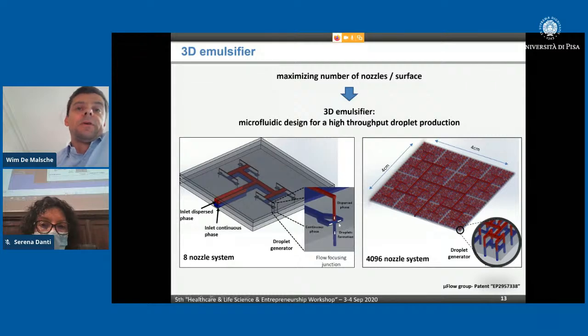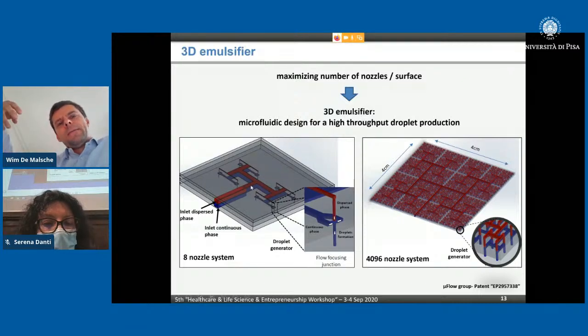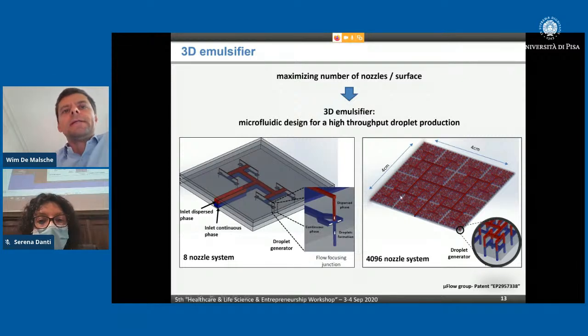The solution to this is what we've been working on now for a few years: instead of having these channels where we form the droplets in the plane, we tilt it and we basically make these channels vertically. By doing so, you can have a plate which is perforated with many nozzles at a very high density. Now we're not paying with big footprints to make each connection, because we make the connections in different layers. In the next layer and in the layer behind, we can make hierarchical structures with flow distributions. Then we have large channels connecting to many of the small channels. We can repeat this if needed, but we don't always do that. With this, we can, for example, have a 4 by 4 centimeter plate having 4,000 nozzles. As you will see later on, this can produce really considerable flow rates.